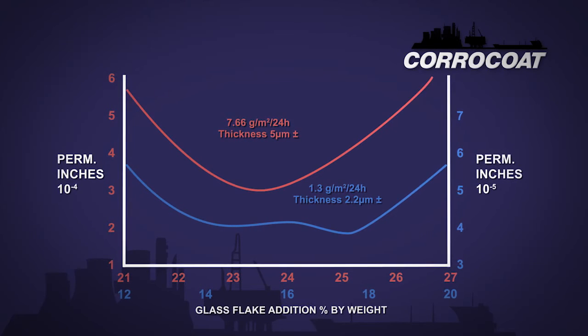Take a look at this graph. The only difference between these materials is the quantity and flake thickness. If you look at the red graph, the 5 micron thick flake, you can see that the lowest permeation rate is with circa 23%, equating to 3 by 10 to the power of minus 4 perm inches. Whereas, if you look at the blue graph, the lowest permeation rate is at only 18%, equating to 4 by 10 to the power of minus 5 perm inches. It's almost a magnitude better.